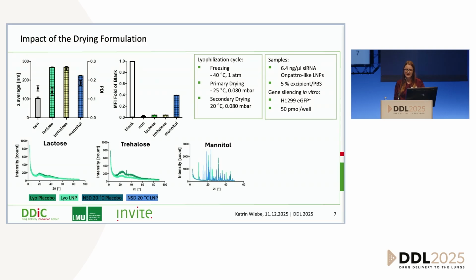These are XRD data of lyophilized lactose and trehalose, where you can see that there's a really nice and smooth curve. So these dry amorphously. And the mannitol, no matter what we do, if we nanospray dry it, if we lyophilize it, if we add LNPs, if we don't, it always dries in a crystalline form. And this is not as good in stabilizing LNPs as an amorphous matrix would be.